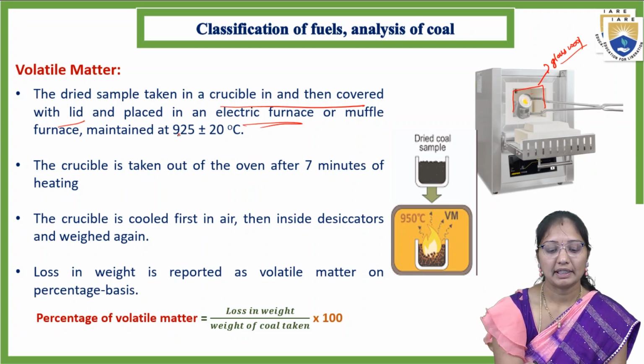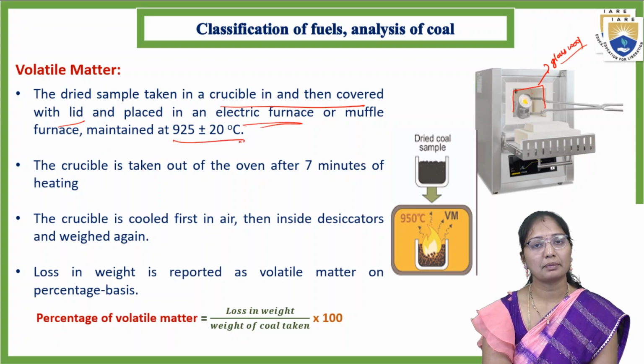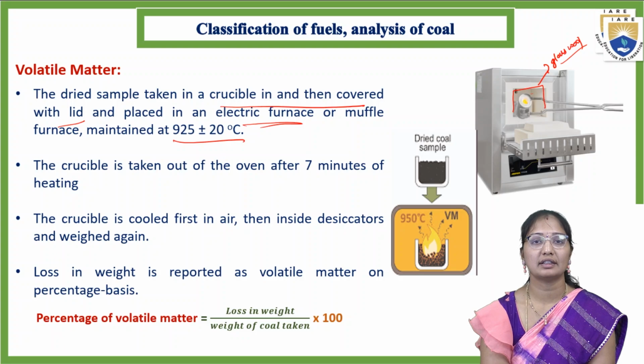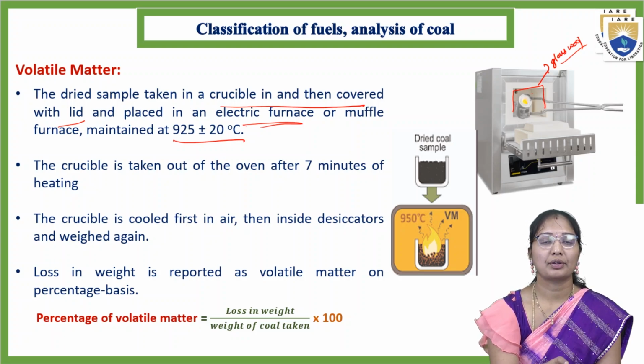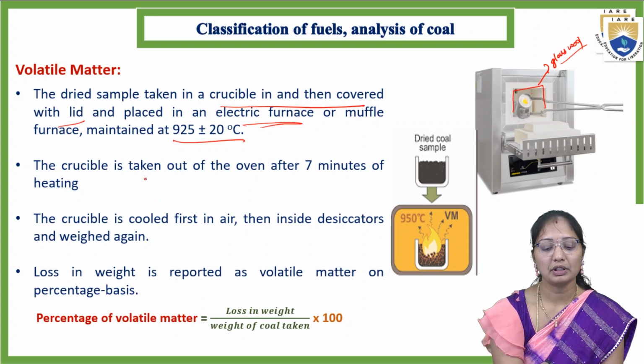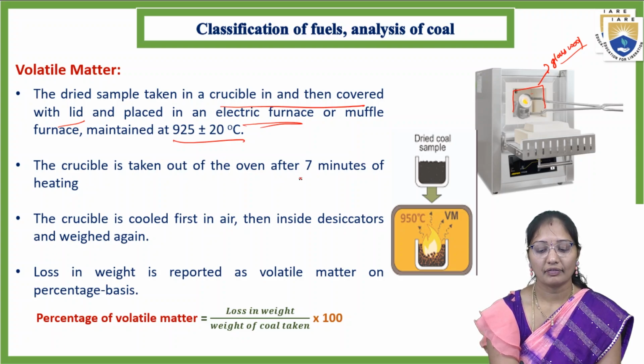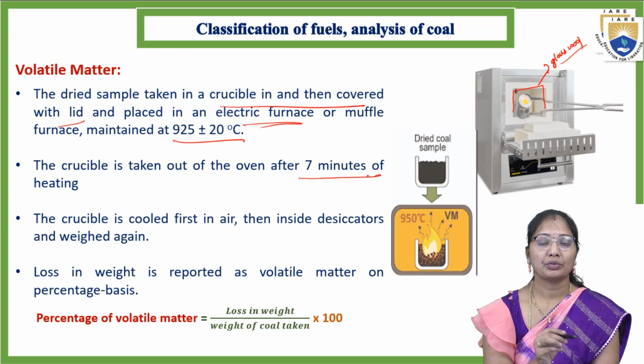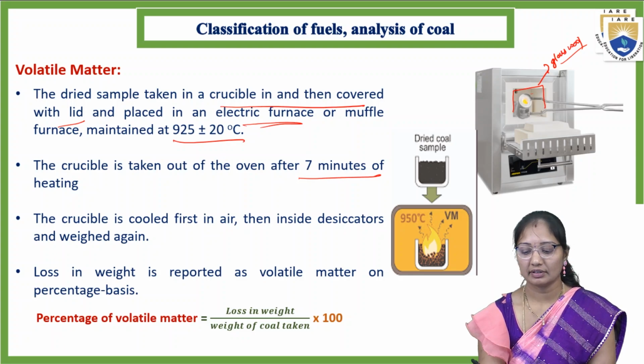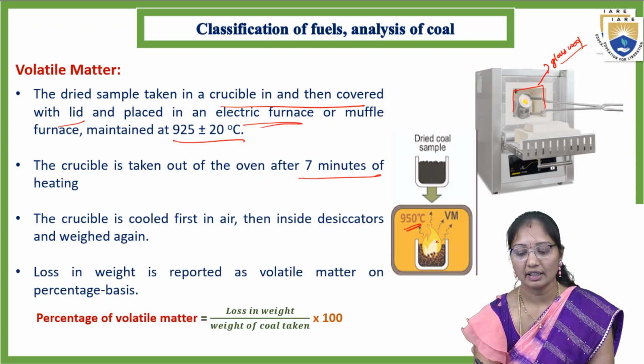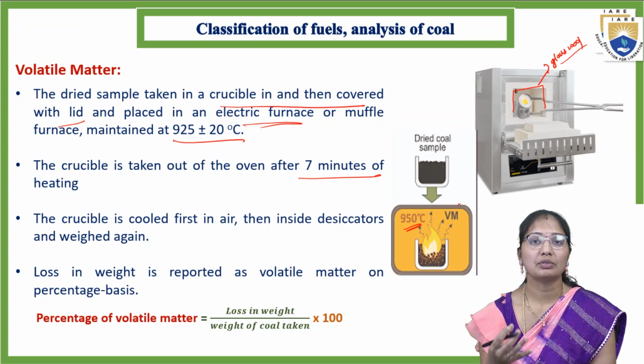This is maintained at 925 plus or minus 20 degrees centigrade, around 950 degrees centigrade. The volatile matter is what we are going to find out. The crucible is taken out of the oven after 7 minutes of heating, so we have to heat it for 7 minutes at 950 degrees centigrade. The matter which is volatile in nature gets evaporated.